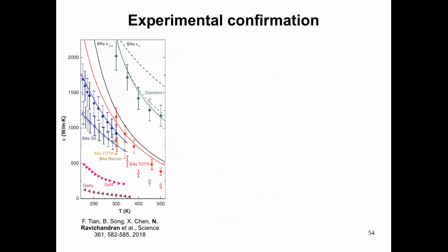To confirm that, we collaborated with our experimental colleagues who fabricated, actually grew, these crystals of boron arsenide for the first time in a very pristine manner with very few defects, and they were actually able to confirm our theoretical prediction. The black solid line that you see here is the calculation from our work, including both 3 and 4 phonon scattering for boron arsenide. And this curve lies very close to their best samples, which are shown by the red circles.